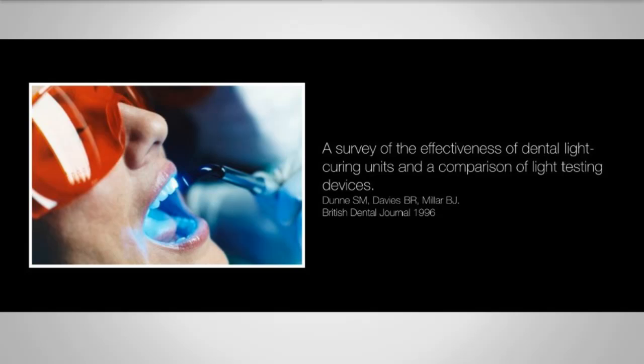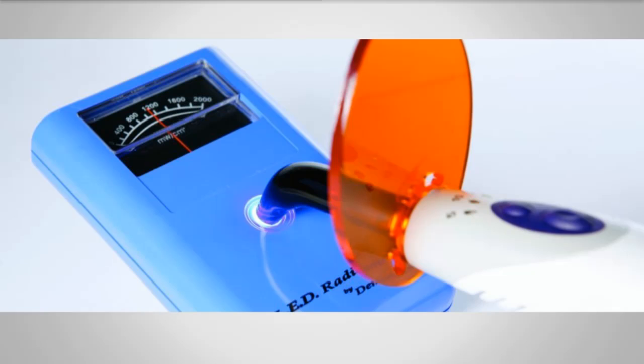There was perhaps bits of composites stuck on the end of the light cure unit, which were reducing the effectiveness, or perhaps there was chips or marks on the end of the light cure unit, or just that the light power had reduced in effectiveness. So it is very important to test your light cure units. It's less of an issue with the LED lights than with the old halogen lights. But you should be testing your unit, I think, at least once a month, just to make sure it's giving you the output that you want and that you think.